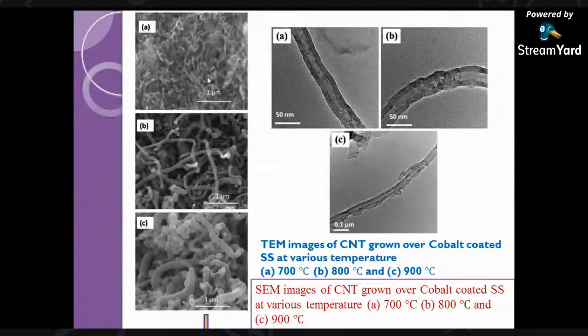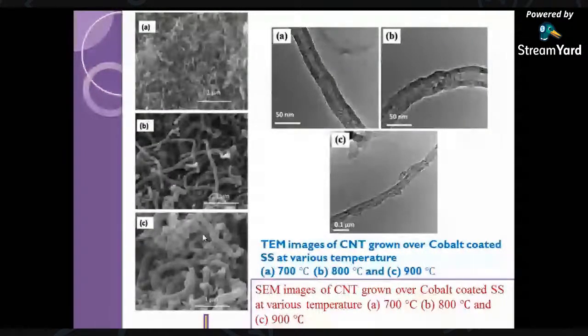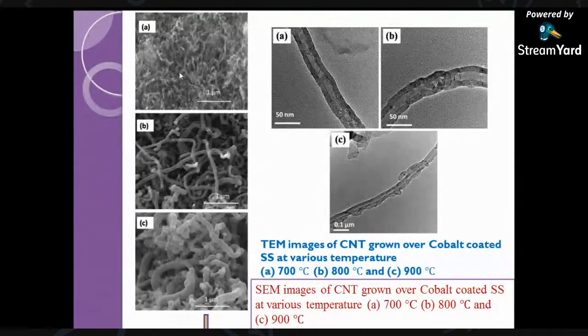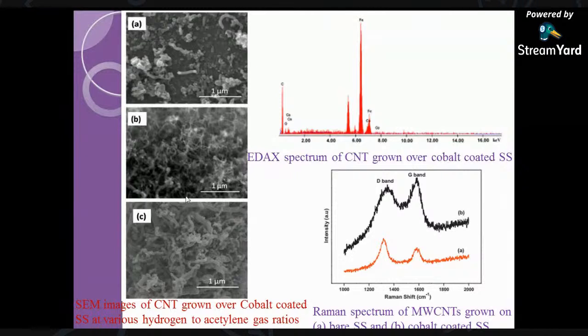Okay, so we tried to do this optimization by running reactions at various temperatures: 700, 800, and 900. You can see the changes happening in the structure of carbon nanotubes. We have thin, thick, and even thicker carbon nanotubes at different temperatures. And this is the TEM image, which shows again different morphologies of carbon nanotubes at the different temperatures. You can see that when we increase the temperature, the thickness decreases, and there is a little amorphous carbon deposited over this.